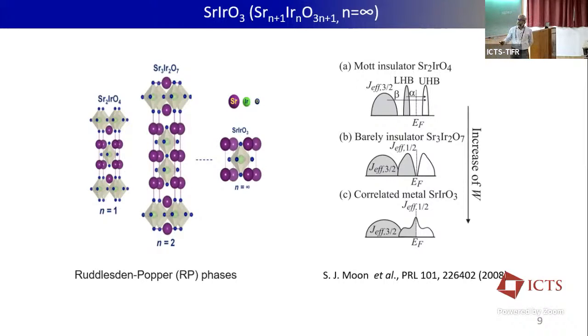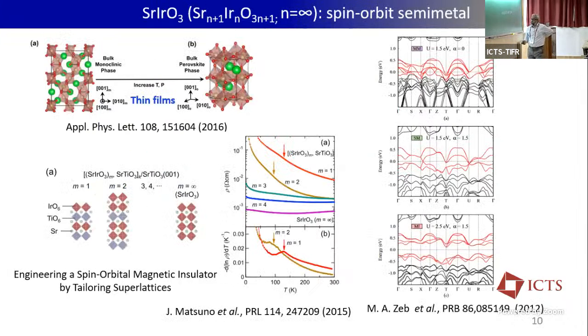Naively, one should expect that if Sr2IrO4 is an insulator, where there is a gap between the J effective one-half bands, then when you increase the dimensionality, growing from n equals 1 to n equals 2, the bandwidth will increase. This is J effective 3/2, and there is an overlap here. When you go to n equals infinity, one would expect that SrIrO3 will be a metal, because there will be overlapping of the J effective 3/2 and J effective one-half bands, due to the increase in dimensionality. But what has been found, as I mentioned, is that to get this SrIrO3 perovskite phase, you can only grow it in thin film form. Either you grow it at extreme conditions of high temperature and pressure, or you introduce strain so that you stabilize it.